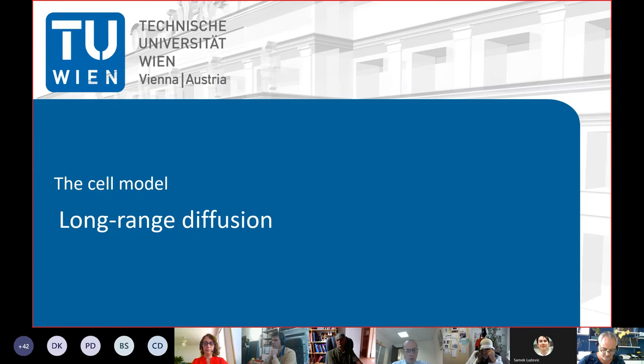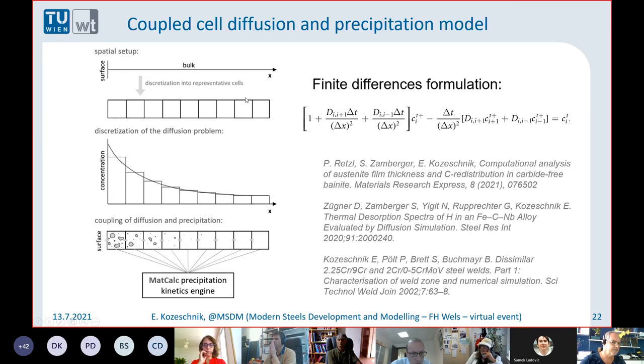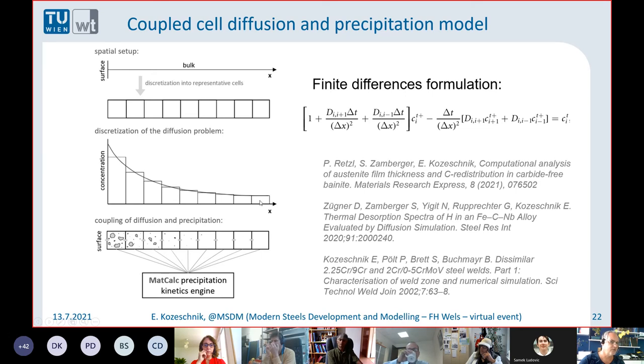One part of MatCalc that I have not very often presented is the cell model, which is used for long-range diffusion. It is actually a very simple model: when you look at the spatial setup of a reaction where you have the volume of the sample, the first step is to discretize into so-called representative cells. Each of these cells is now some kind of an individual MatCalc instance. Each cell can perform all the kinds of simulations you can do in MatCalc, just in a spatial arrangement. One feature is that cells can communicate with each other via diffusion fluxes — using a simple finite differences formulation — and another feature is that in each cell, MatCalc can perform precipitation kinetics simulations.